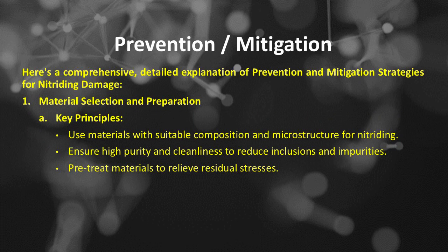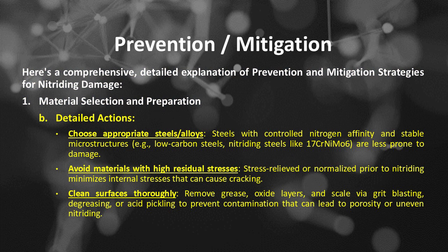Number 1 of prevention and mitigation strategies for nitriding damage is material selection and preparation. The key principles include: use materials with suitable composition and microstructure for nitriding, ensure high purity and cleanliness to reduce inclusions and impurities, and pre-treat materials to relieve residual stresses. Detailed actions include choosing appropriate steels or alloys, steels with controlled nitrogen affinity and stable microstructures, such as low-carbon steels.